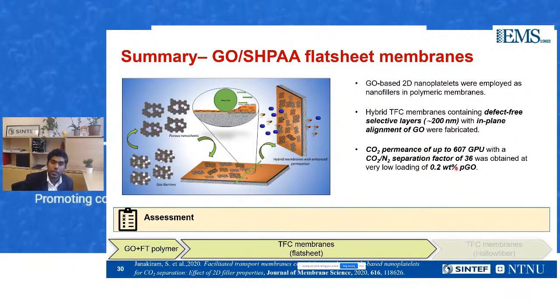And for the CO2 permeance and selectivity, we were able to reach very optimal numbers with just 0.2 wt% of porous graphene oxide. In this assessment, the performance is quite nice, and the stability of the membranes is very good, because we tested up to 1.5 years. The processability of the membrane is also good because we were able to coat a 200 nanometer selective layer. That is what is needed for this application.